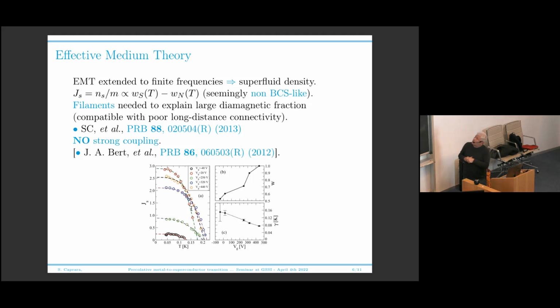And the superfluid response is very, very much different from the superfluid response of a homogeneous superconductor. Why? Because, again, the width of this superfluid response is ruled by the width of the distribution of your critical temperature of disorder in your system. So you have a hint for an inhomogeneous superconducting state, even if you measure the finite frequency response below the superconducting critical temperature. Sorry, Sergio, there is a question online.